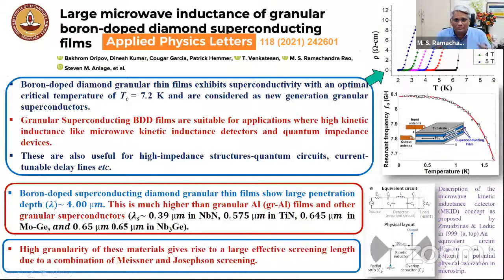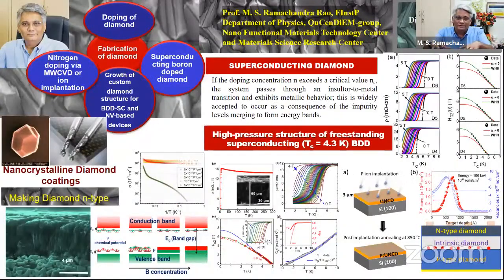You need to do a lot of characterization. Nitrogen can be doped with only implantation. You implant these nitrogen ions and then anneal the sample, and then you get nitrogen getting into the lattice, giving rise to 1 electron. And it also creates a vacancy. So these nitrogen vacancies are the fundamental elements for quantum bit fabrication. So these are called NV centers.